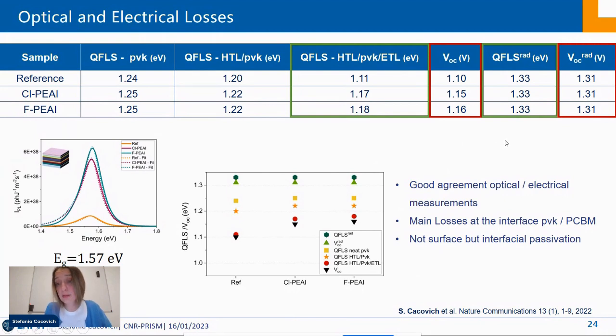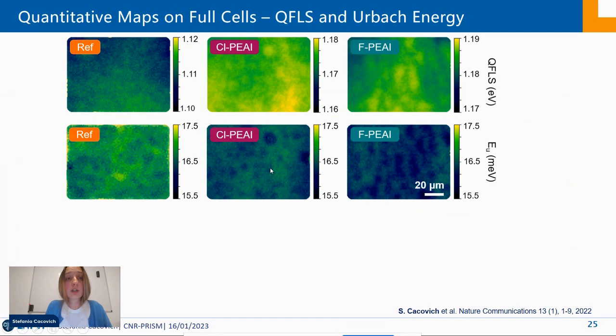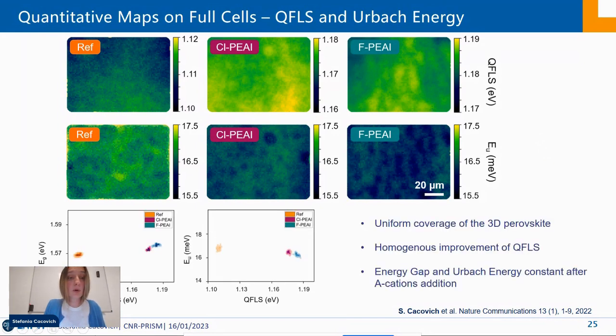So we have a good agreement, as I mentioned before, between optical and electrical measurements. And also we can say that the main losses occur at this interface. And finally, I show you the maps I was mentioning before, on both delta mu and here the Urbach energy, which is another parameter related to the defects of our material. Here we just correlate pixel by pixel the variation of the gap as a function of the variation of the quasi-Fermi level splitting, and the Urbach energy as a function of the quasi-Fermi level splitting.